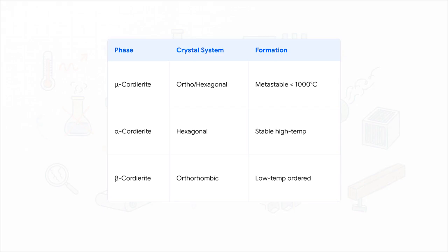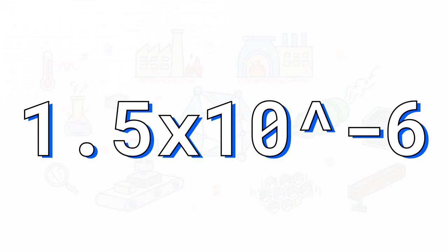But the MVP here? That is alpha cordierite, also known as indialite. This hexagonal, high-temperature stable form is the undisputed industry standard. It's this specific disordered arrangement of aluminum and silicon atoms within the crystal lattice that unlocks the ceramic's absolute greatest physical trait. And that trait is perfectly captured by this incredibly tiny number, 1.5 times 10 to the negative 6th per Kelvin. That is Cordierite's coefficient of thermal expansion. In plain English, when you heat this material up, it barely expands at all. In fact, along certain crystal axes, the thermal expansion is basically near zero.